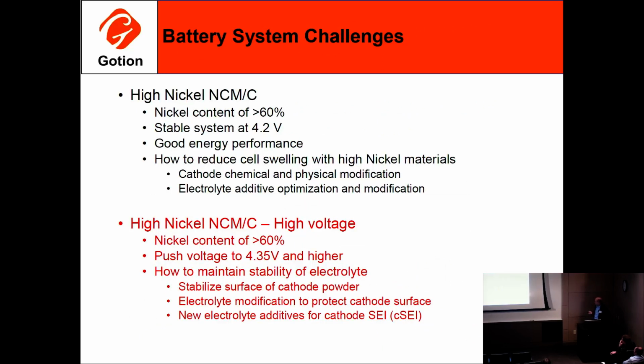It looks pretty good. On the bottom half, the other way to increase energy density is to increase the voltage. You take this 4.2 here and you go 4.35, 4.4, and that's what we're looking at as well. But again, as voltage goes up, stability of the electrolyte starts to become questionable. It's another source of gassing when you increase the voltage. So you've got the high nickel problem to start with, and you add another problem on top of that. This is where we start to look at what we call the cathode SEI.